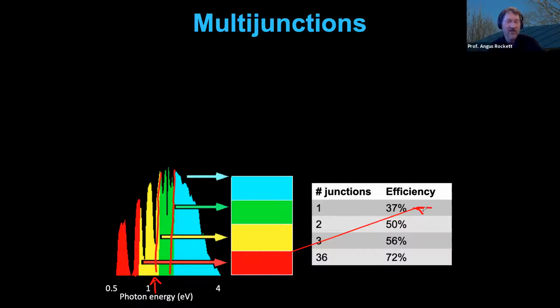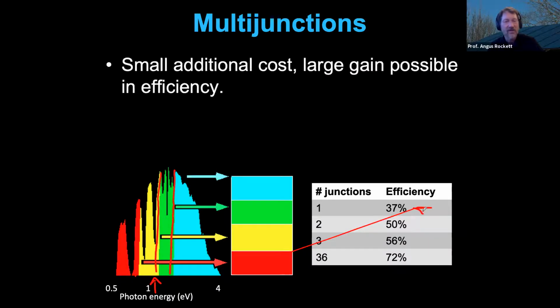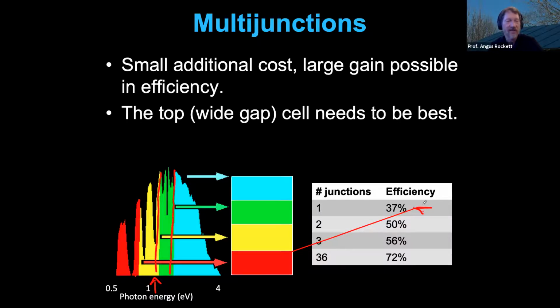There are 6-junction solar cells that have been made in these very high efficiency space-based solar technologies. They're in the range of 45, 47% efficient. So the thing about multi-junctions is that with a small additional cost, I can make 2 solar cells instead of 1, have a large gain in efficiency with relatively little additional cost if I can make a good solar cell in the blue part of the spectrum. So that top so-called wide gap cell needs to be the best, and it needs to be very good. It's also unfortunate because that's the hardest junction to make a good solar cell out of.